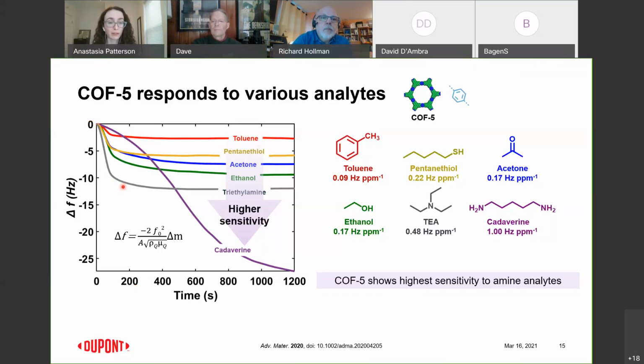You can see already that there's a wide range of responses to different gases based on this particular material. There is higher sensitivity for amines like triethylamine, so that's a good sign for potentially using these materials for amine sensing. But you may notice that one of these curves is not really like the others. Cadaverine here has a very strong response and a very slow equilibration time compared to the others. There are a number of chemical reasons for that, but there's also a geometric reason, which is another reason why these materials are so cool.